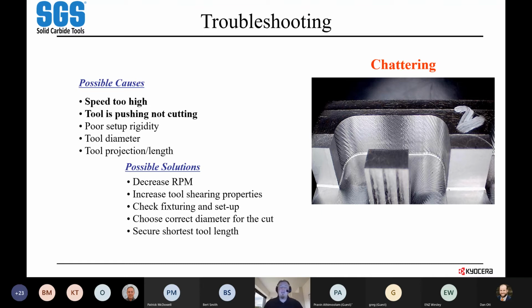Another thing it could be is tool diameter. So like in this case in the picture here, having a large diameter tool going in and driving these corners, it's going to have a tendency to grab once it hits this higher engagement in the corner on a larger tool and jump. And so once it starts to jump, it's not going to stop. So you're going to see that run all the way through. It's going to hit this corner again. It's going to basically repeat itself.